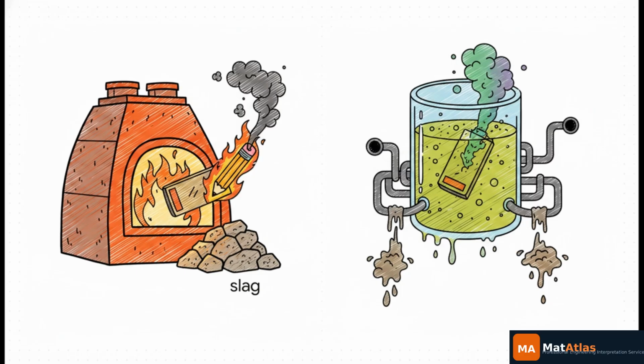On one hand, you have pyrometallurgy, which involves melting down materials in massive furnaces at extreme temperatures. We're talking 1100 to 1500 degrees Celsius. It wastes a ton of energy, it totally incinerates the valuable graphite, and thanks to the stability of the slag, the lithium is often just lost entirely.